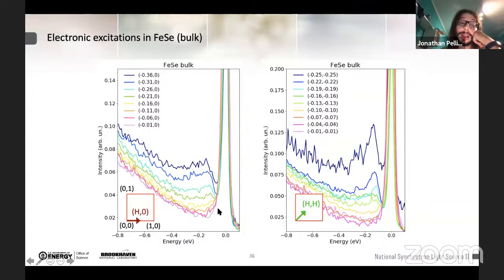And this was observed for both crystallographic directions that we have investigated, the H0 direction and the HH direction, where you can see that along both of them, we have a pretty strong spin excitation dispersion, where we have high energy at high Q, and as we decrease the Q, we decrease the spin excitation energy.